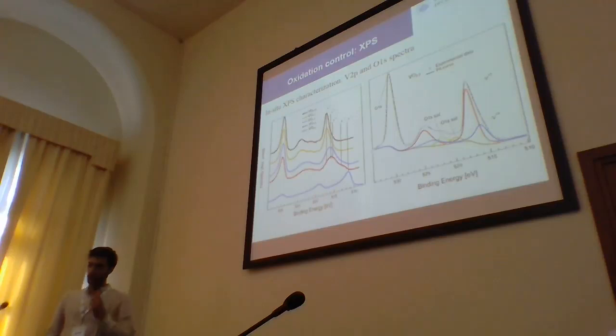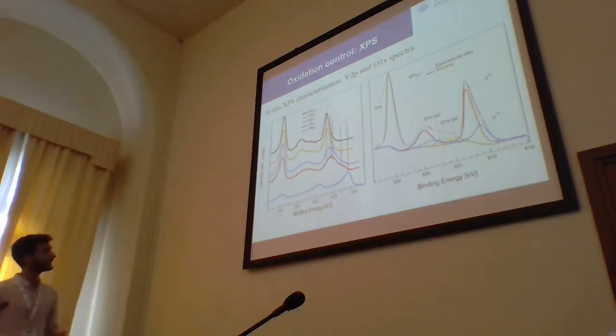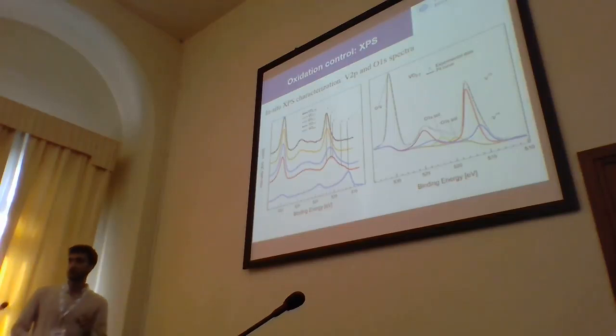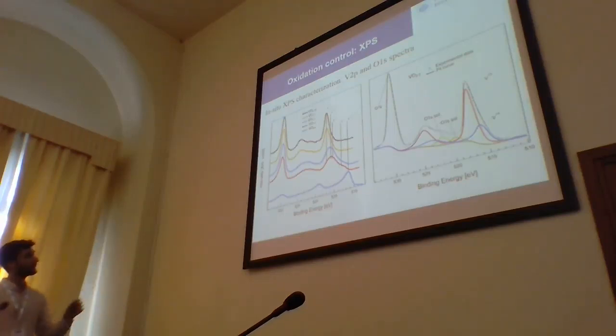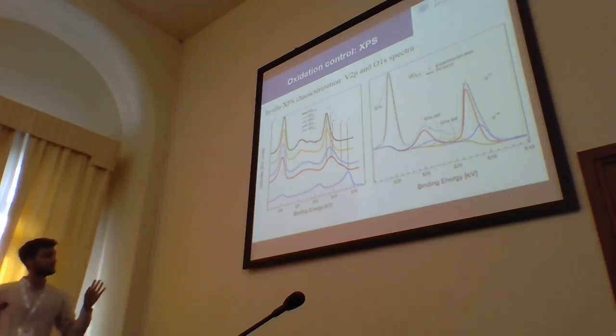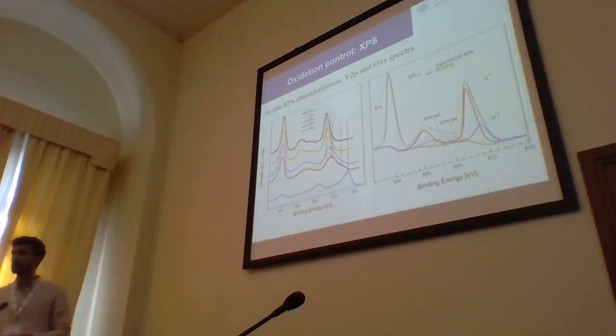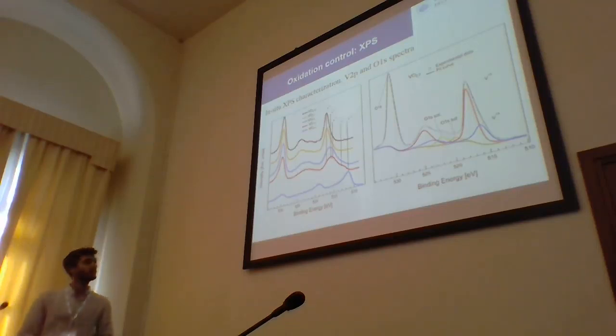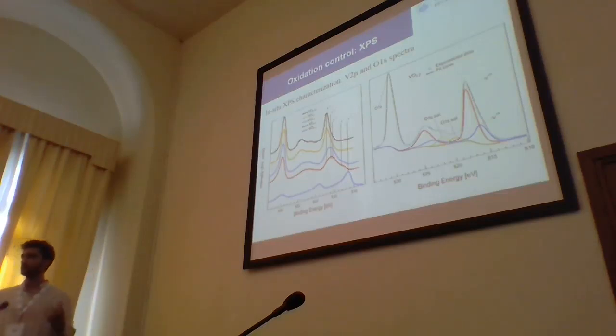So in the left graph are depicted the vanadium 2p and oxygen 1s spectra. You can see the shape is changing, and to obtain quantitative information from these spectra, I used a fitting procedure. In this way, I was able to isolate the vanadium components, which are linked to different vanadium oxidation states. Making the ratio of the areas of these components, I was able to extract the stoichiometry.